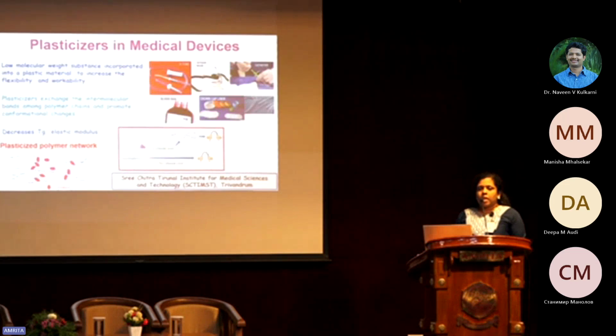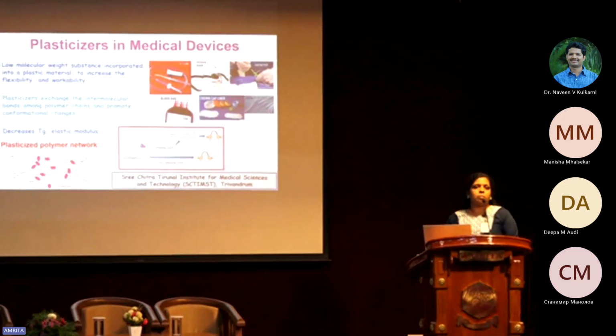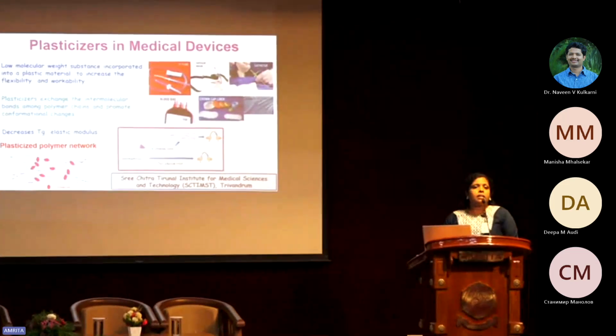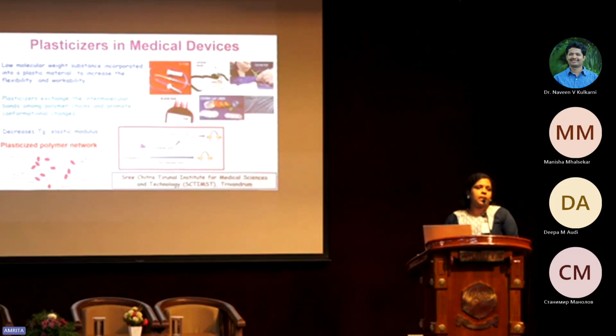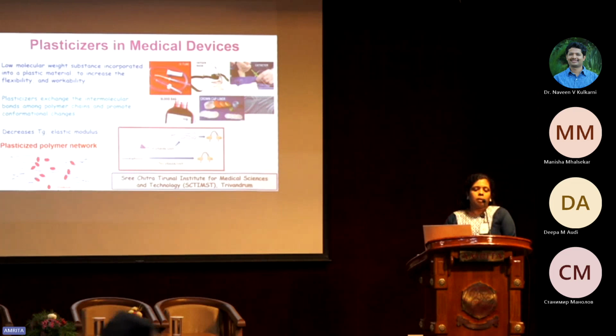And the conclusion. So, what is a plasticizer? Maybe you all know, it is a low molecular weight substance or an oligomeric substance that is incorporated into the plastic material to increase the flexibility and the processability of the material. The plasticizers exchange the intermolecular interactions between the polymer chains and form interactions between the plasticizer and the polymer chain, so that it can promote conformational changes and introduce flexibility to the polymer matrix, which decreases the Tg, that is the glass transition temperature of the system, and the elastic modulus.